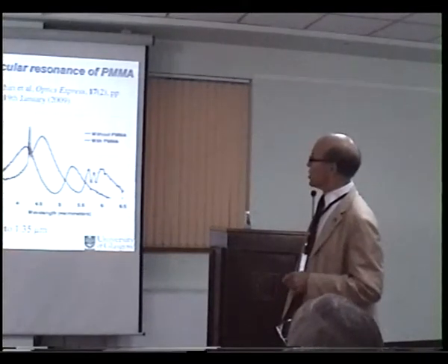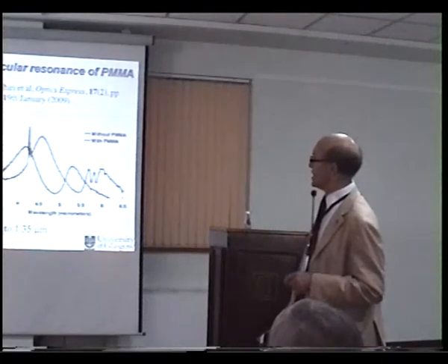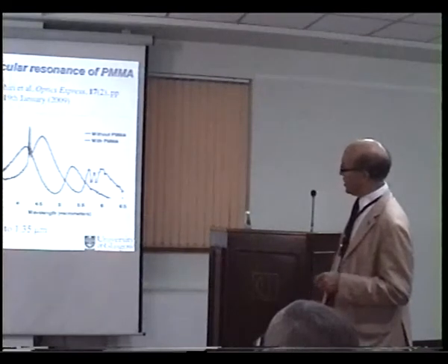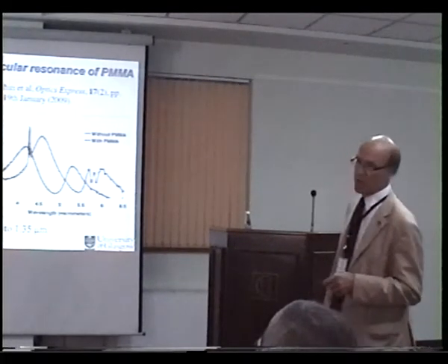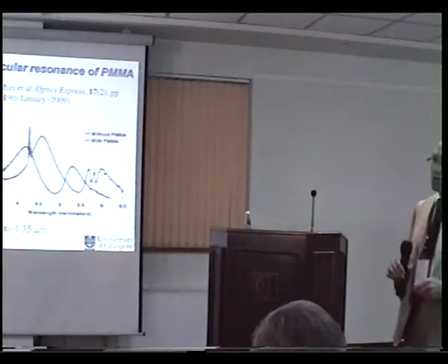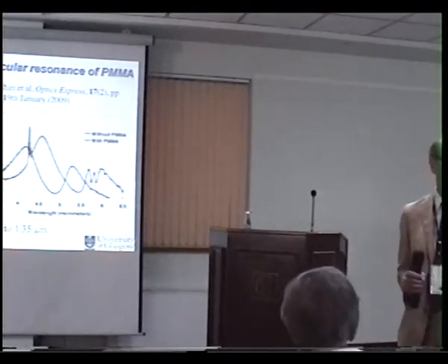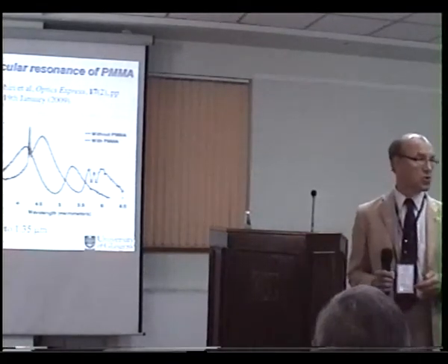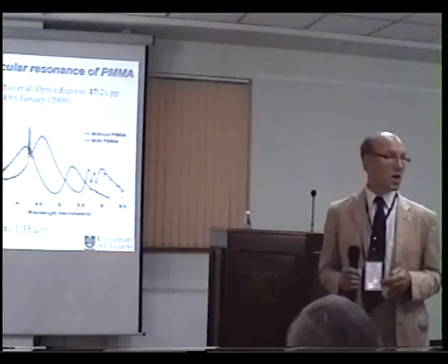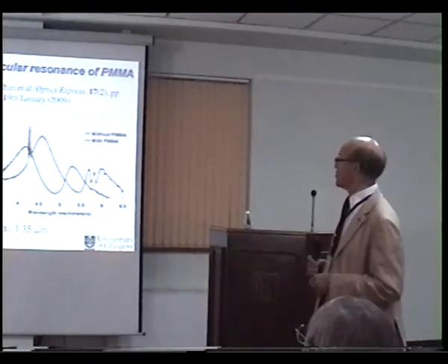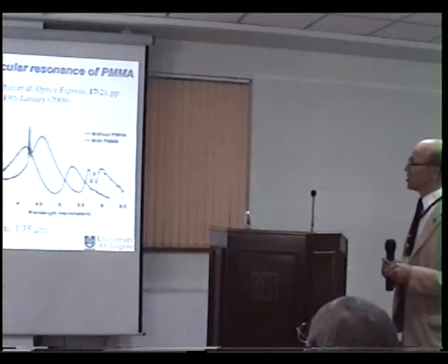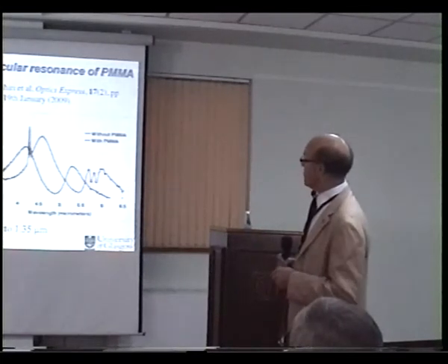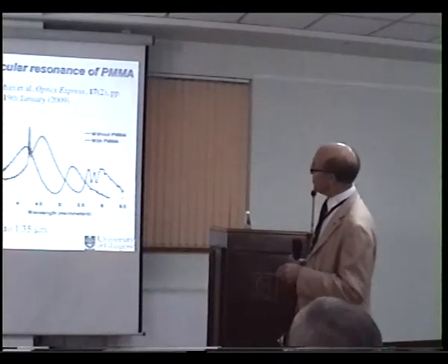That's just another image of a particular structure fabricated, so this is one element. This was published a little while ago. If we take an array of these elements and we deposit an organic material, which indeed could be a biologically derived organic material, and I'm using the word organic slightly more strictly in the chemistry sense, that is compounds made of carbon. And the compound made of carbon that we put onto the surface is polymethyl methacrylate. So we are depositing a thin layer of PMMA, and we take these resonances in the reflection.